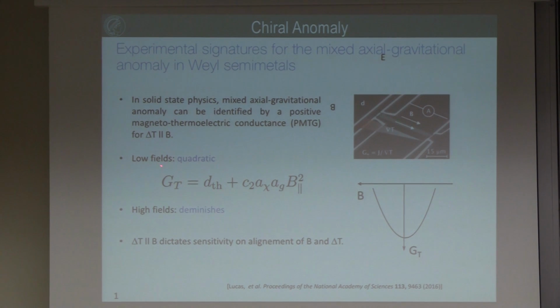And the condition was that if you measure this magnetothermoelectric conductance, it should go with a B square, again very similar like the conductivity, and at high field. But here it should change from the quadratic behavior because it should diminish at high fields, and it should be aligned. There should be a strong alignment between the temperature gradient and the B field. So this was a prediction.